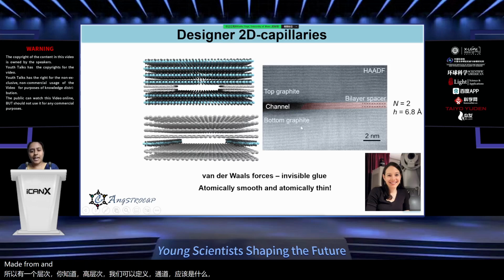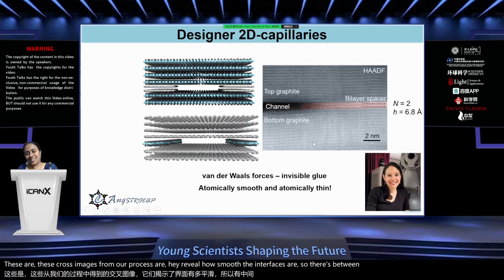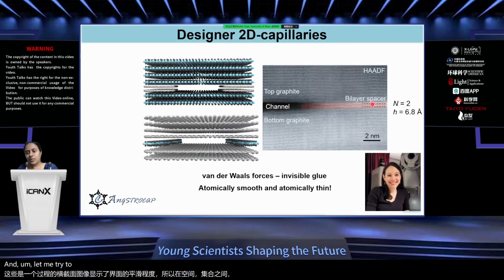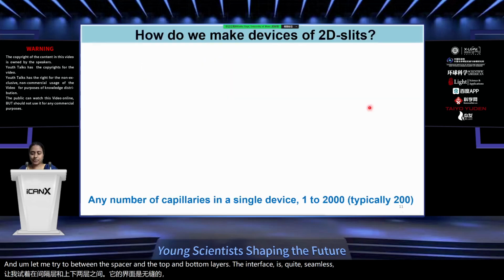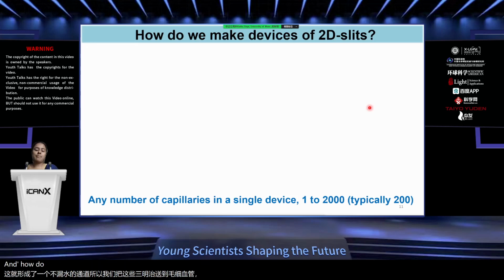And these beautiful cross-sectional images from Professor Sarah Haigh reveal how smooth the interfaces are. Between the spacer and the top and bottom layers, the interface is quite seamless, which makes it a leak-tight channel. So we make these sandwiches of 2D capillaries, and how do we measure flows through them?